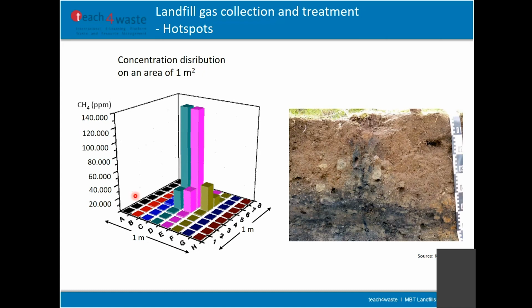And if you open the soil in this area, you will see such a channeling. Here the black area is showing you that the methane is in this area in higher concentrations. We have anaerobic conditions. And here we have some fissures inside, some openings, and the gas can flow very easily to the surface. So here also this black color, and if you are taking a sample on the top, you will get these high concentrations, these high peaks. And this you cannot avoid.